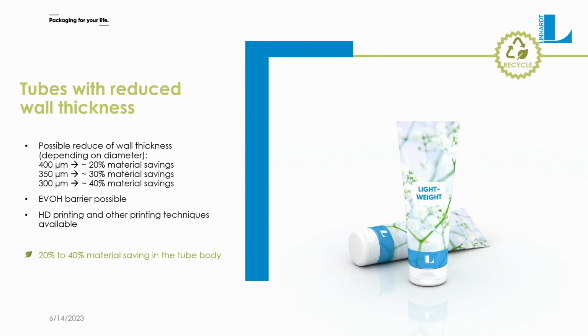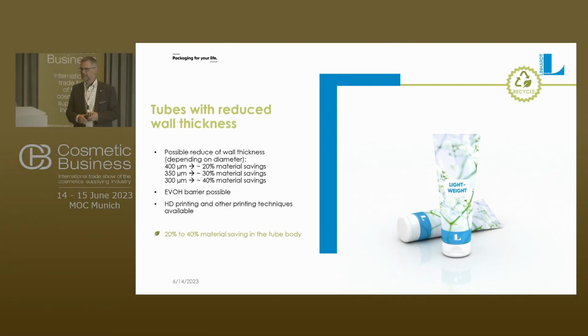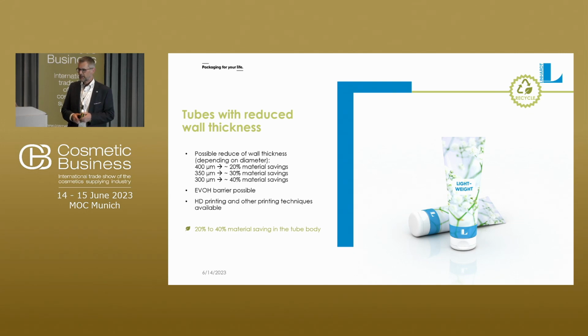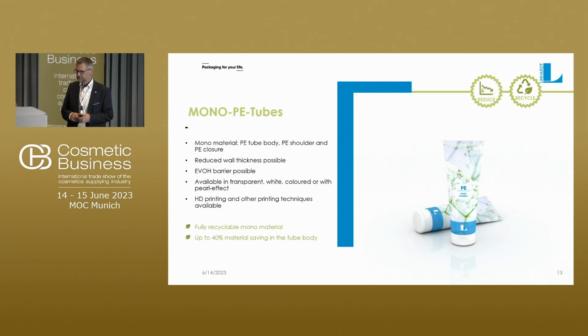We try to reduce that as far as possible, and with new EVOH generations, we can successfully cut the EVOH barrier thickness in half while still offering the same performance. Like the barrier properties are the same, but we only use 50% of the EVOH barrier thickness. This means that compared to the original tubes that we offered like 3 or 4 years ago, we now have a tube that uses 40% less material in the walls. So 40% less CO2 emissions.